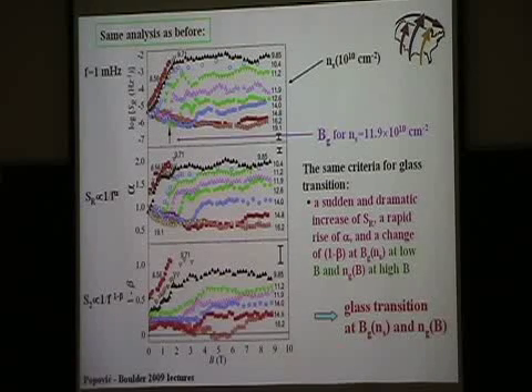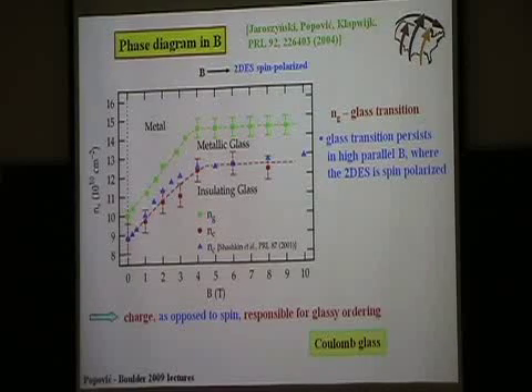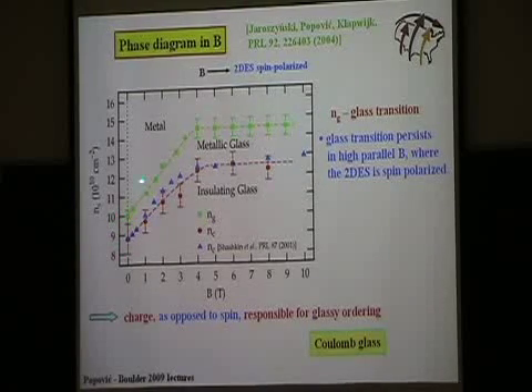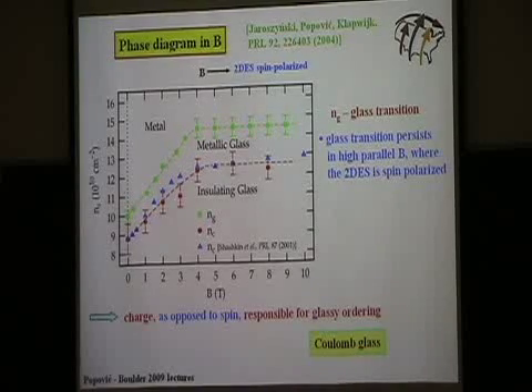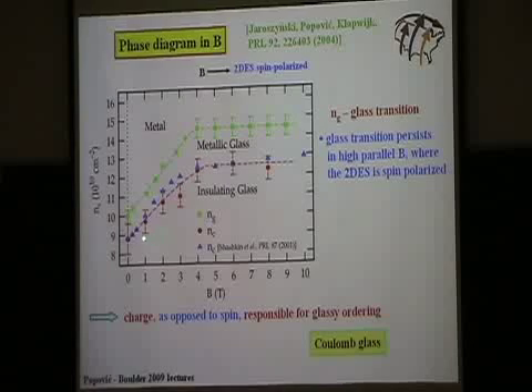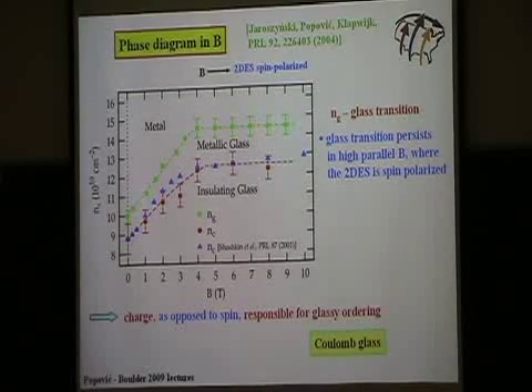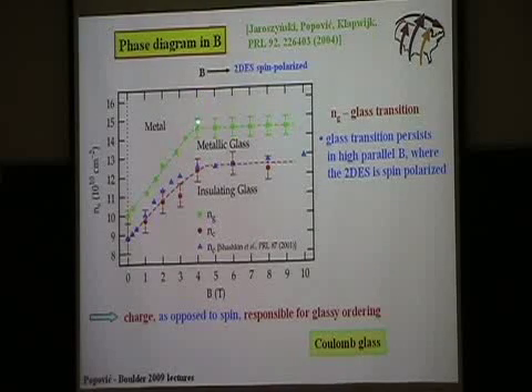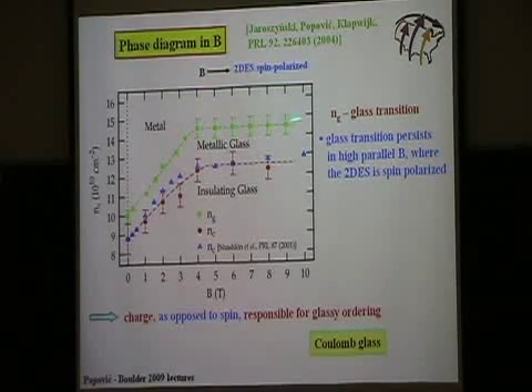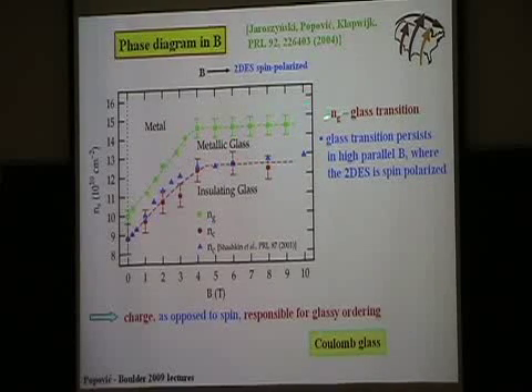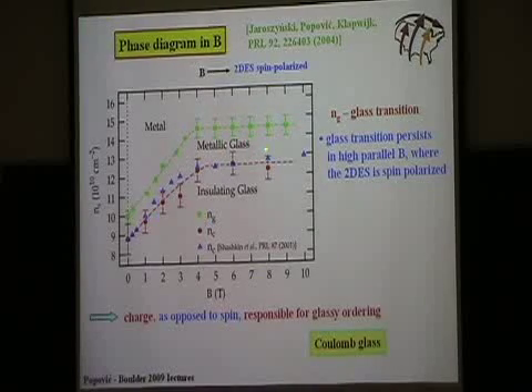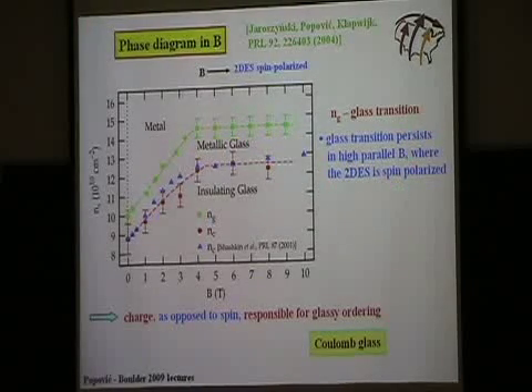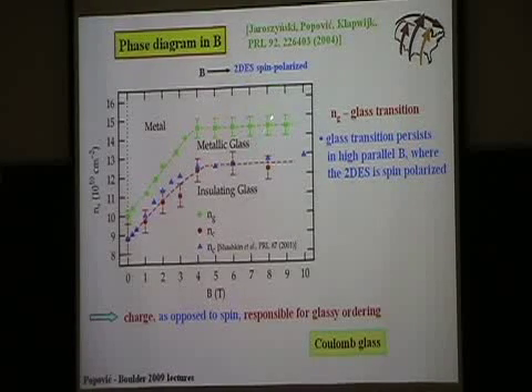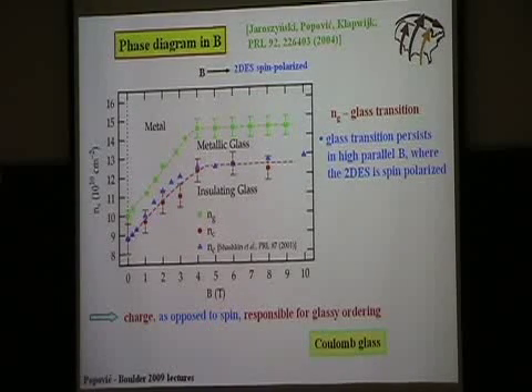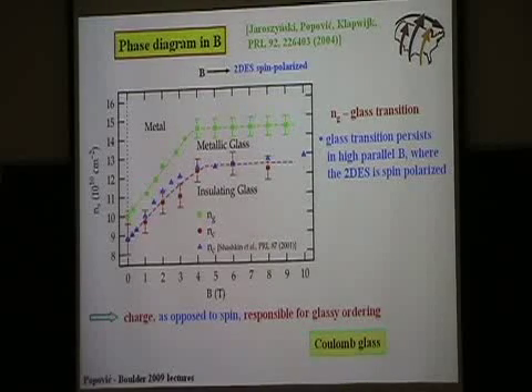So in this way, you can map out the phase diagram, which is what I showed you yesterday. So these green squares are the data that we obtained from this kind of analysis. So this is where the glass transition takes place. This is the metal-insulator transition. And you can see that at a field of about 3 Tesla, when the system is fully spin polarized, nothing depends on the magnetic field anymore for these values of densities. However, the glass transition persists. So even when the whole system is spin polarized, we have essentially a system of spinless electrons, the glass transition persists, and this tells us that it is the charge degrees of freedom as opposed to spin that are responsible for this glassy ordering, so we do have a Coulomb glass.